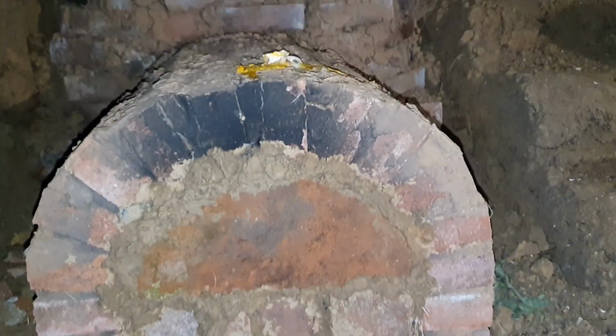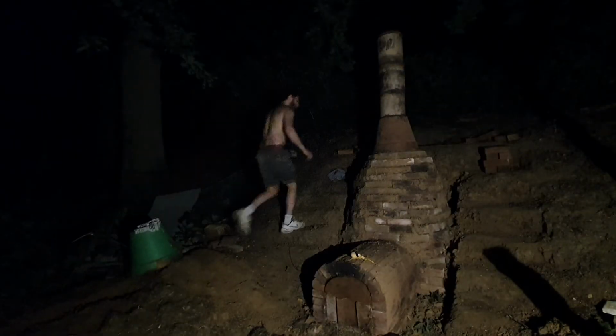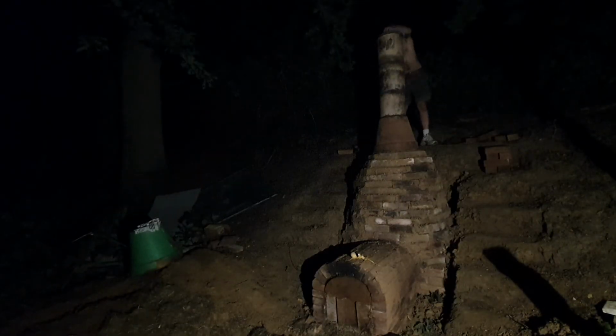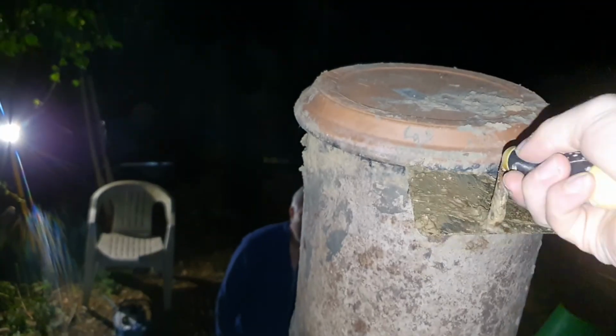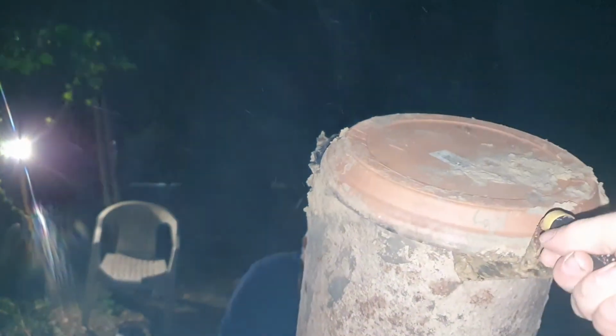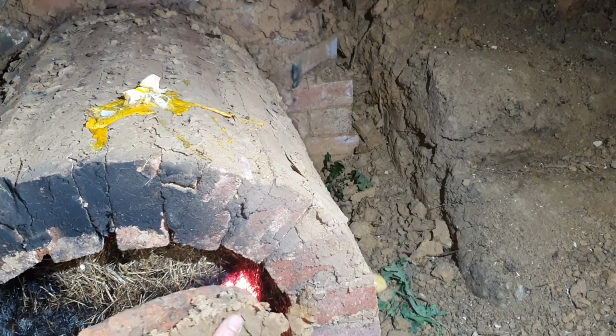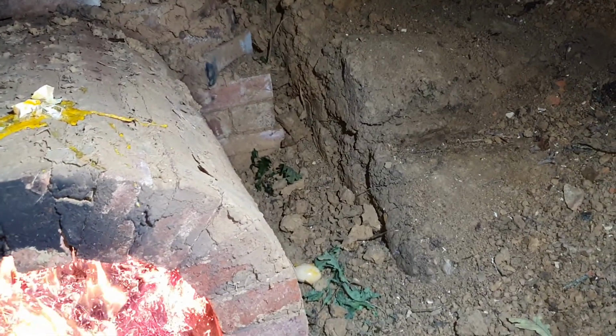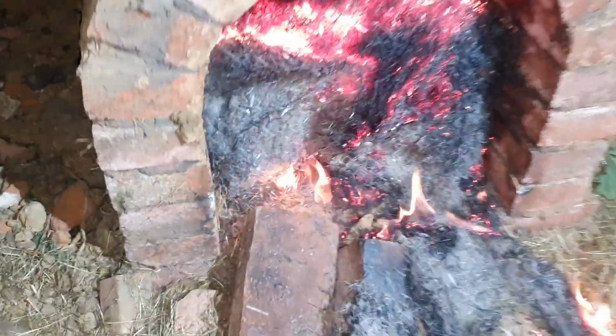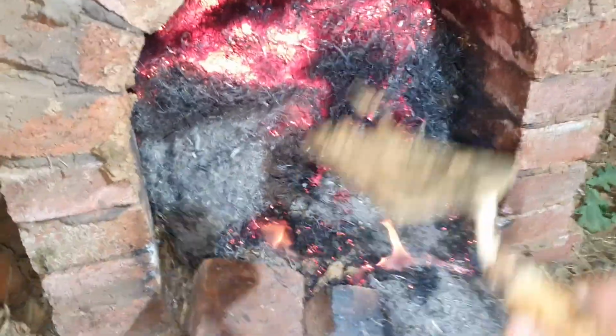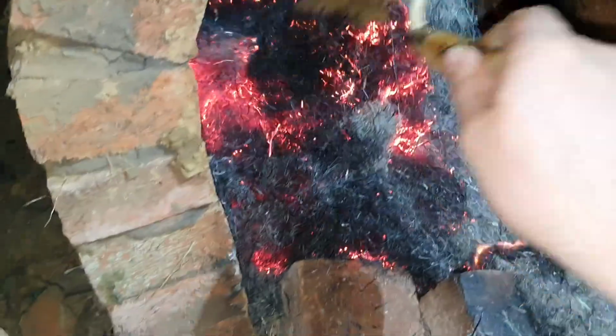After closing the kiln, I then began to seal any leaks I found, using damp clay. After waiting an hour, I now felt they had been long enough for the kiln to be reoxidized. I could only hope they had continued to maintain temperature, and that vitrification had taken place with the carbon sealed. Upon opening the vents and door, reoxidization would cause rapid combustion of the dried fuel, and I hoped would reoxidize the body of the pot, returning it to a red colour.